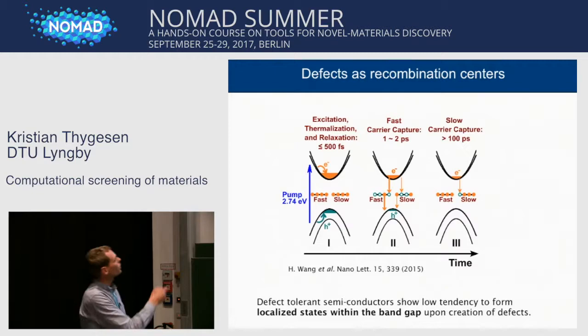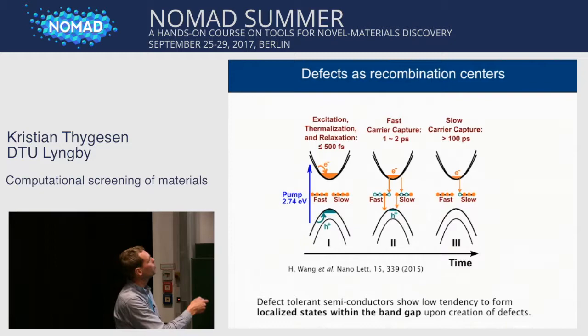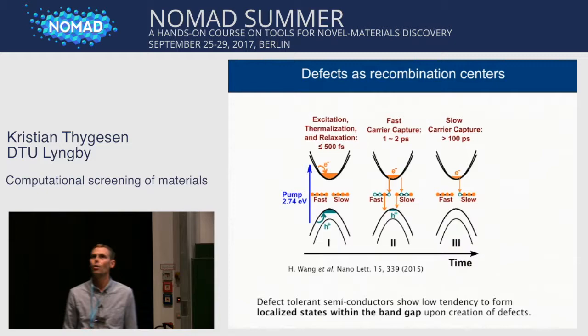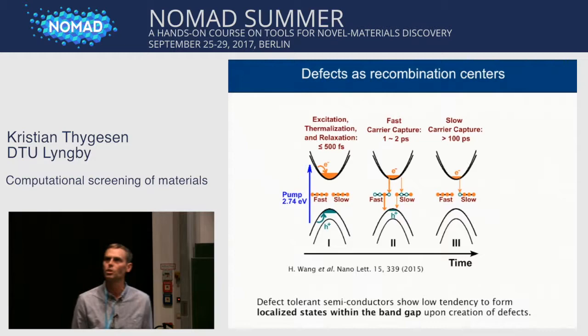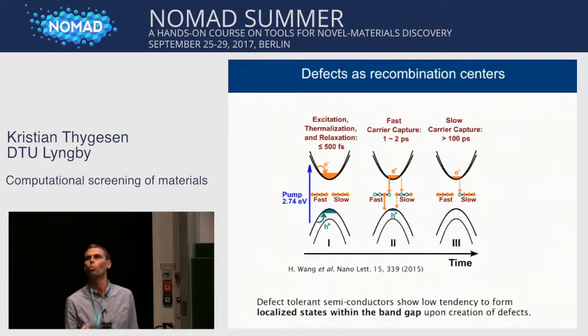You can see an illustration, just a cartoon of what happens if you photoexcite carriers. So very quickly, these carriers will relax in the conduction band and the valence band to form some quasi-equilibrium distribution. But then after a few picoseconds, those electrons and holes will start to recombine non-radiatively through defect states in the band gap. So if we have states that sit in the band gap, they will act as scattering centers and therefore reduce the transport properties of the material, and they will act as recombination centers, where we will basically lose the electron-hole pairs that we've generated by the solar photons. So, ideally, we would like to have materials that are robust against the formation of states inside the band gap. And this is what we call defect-tolerant semiconductors.